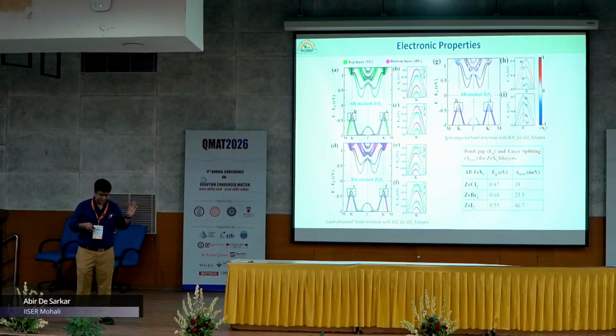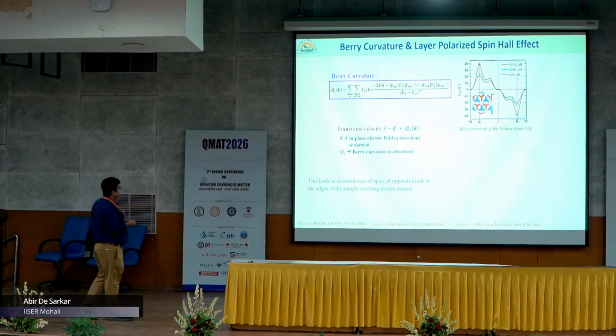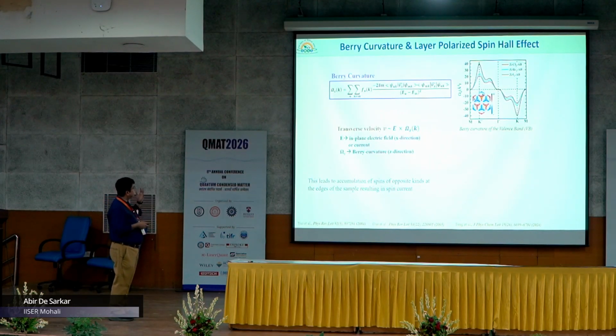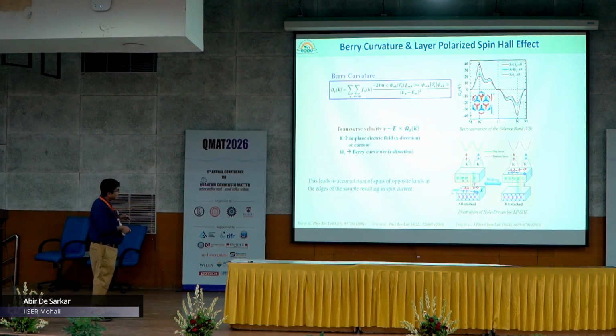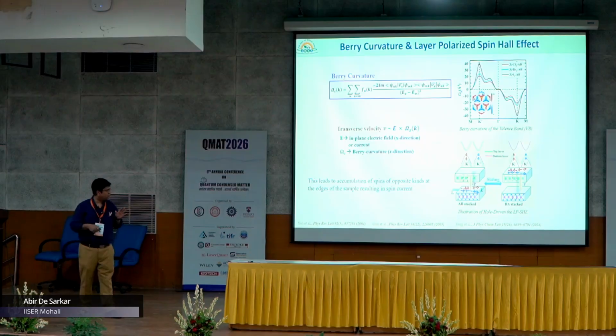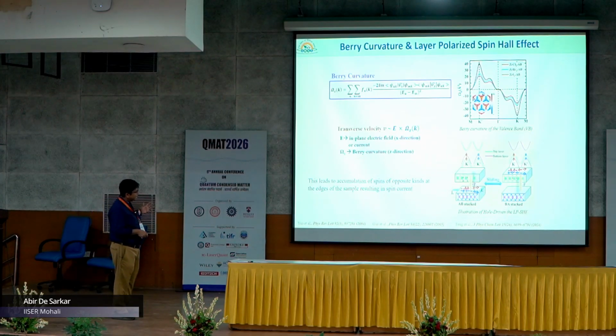That is what we observe over here, and that is what we have calculated: the Berry curvature, the spin Berry curvature, spin Hall conductivity, and the spin Nernst conductivity. All this we have reported in our article, and in summary, what we find is that in this stacking sequence, the valley Hall effect, or the spin Hall effect, will take place in this bottom layer, and in this one, the spin Hall effect would be occurring in this top layer. So one can realize a hole driven layer polarized spin Hall effect.